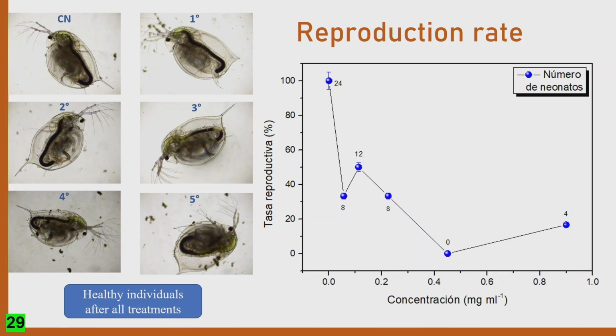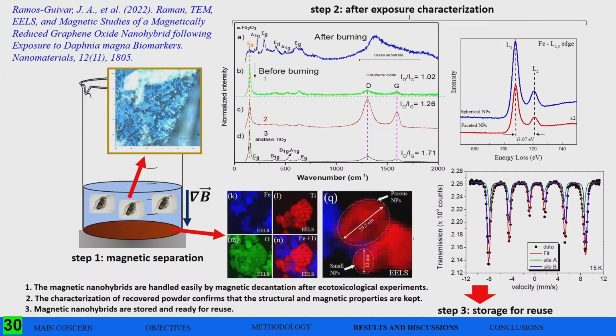The problem comes with the reproduction rate. If we use higher concentrations, the individuals, after 2 weeks of recuperation, cannot give birth to more individuals. So the reproduction rate is being affected, right? But if we are below that lethal dose concentration, we can apply our nanoparticles in a 24-hour exposition.